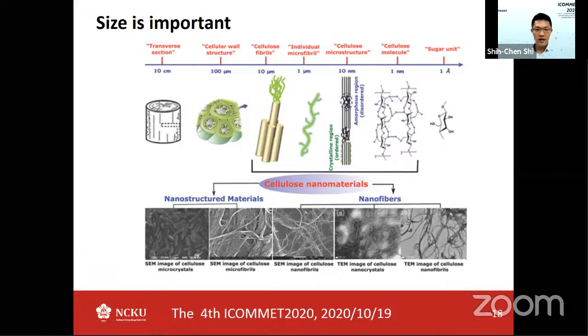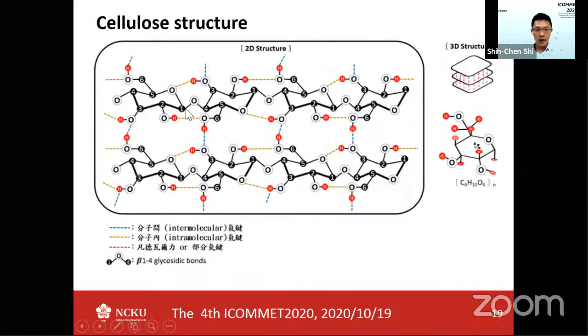We will introduce that later. Okay, the cellulose structure is like this, and this is the sugar unit. It has so many intramolecular and intermolecular bonds, hydrogen bonding, and this bonding makes the cellulose strong, and it can offer very good properties, especially mechanical properties. And actually the cellulose has a 3D structure, so the strength and the hardness of this material is really good.